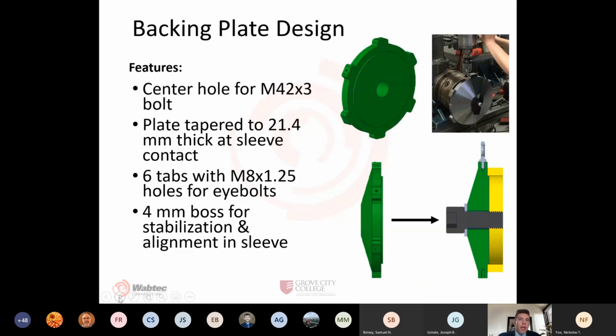The final backing plate design features a clearance hole at the center for the M42 bolt. It also is 50.8 millimeters thick and is tapered down to 21.4 millimeters at the sleeve contact surface. The design has 6 tabs that are equally spaced 60 degrees around the edge of the plate. And these tabs all have an M8 hole that allows for the installation of eye bolts.